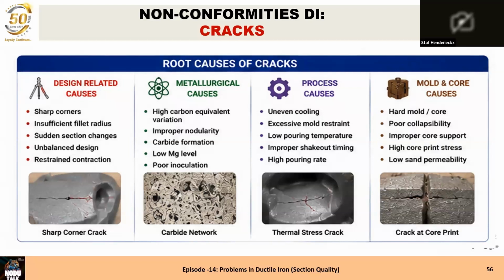Improper shake-out timing, of course: if you shake out and hit them, it can crack. And a high pouring rate is mostly the cause, because with a high pouring rate you make dross and other inclusions, and inclusions are the initiators of cracks later.